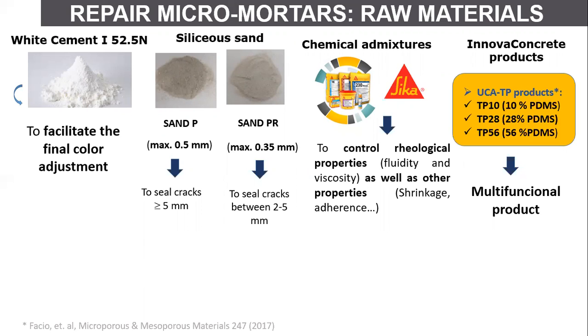In this slide, I show you the raw materials that we have used in the design of the repair micromortar. So we have used a white cement to facilitate the final color adjustment. We have used 2 different types of siliceous sands with different maximum particle sizes, 0.5 and 0.35 millimeters. We will use one sand or the other depending on the thickness of the crack that we want to repair. We have used several types of commercial chemical admixtures, which are going to be incorporated into the mortar to control the rheological parameters, such as the fluidity and the viscosity, but also other properties, the volume stability and adherence.